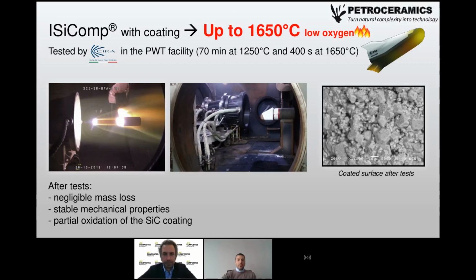Okay. So besides, the samples and the end products were also tested in order to simulate the thermal and oxidative stresses that they will undergo during several missions. So they were tested in the plasma wind tunnel facility by CIRA, and after testing, which consisted of exposure up to 1650 Celsius degrees, negligible mass loss was observed, and mechanical properties were maintained. Only some partial oxidation was observed on the silicon carbide coating, but this was expected, basically.